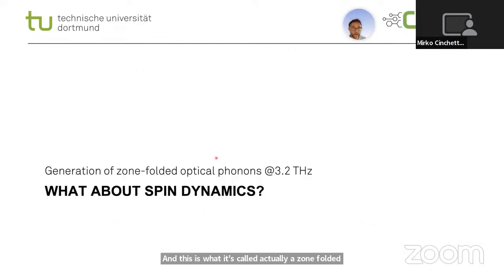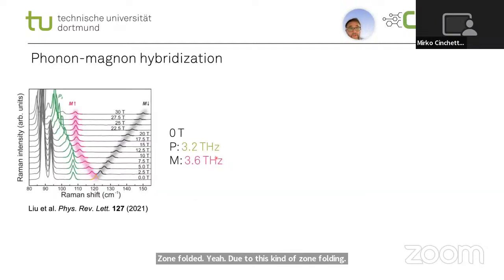Up to now, I've shown that if we excite the d-d transitions, we are able to generate optical phonons, and these phonons feel the magnetic state due to this kind of zone folding. What about the spin dynamics? If you look in the literature, it is reported that this phonon mode hybridizes with a magnon mode in the presence of a magnetic field.